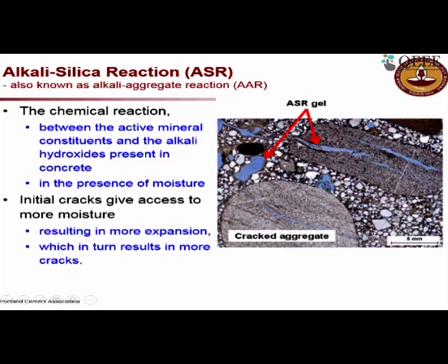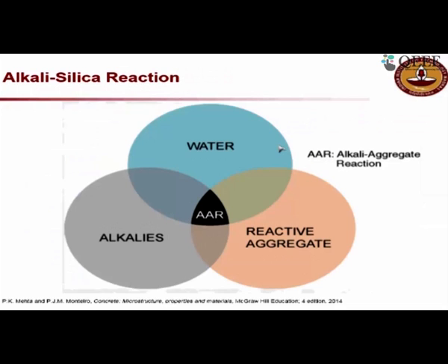This gel can absorb moisture and also expand. When it absorbs, it expands, and then tremendous pressure is applied on the aggregate or the system as a whole, which leads to cracking. Once the cracking happens, it can also lead to further ingress of moisture. So that's an additional problem which comes up. We have to prevent this cracking one way or the other by using aggregates which are less reactive in nature and also cement with low alkali content.